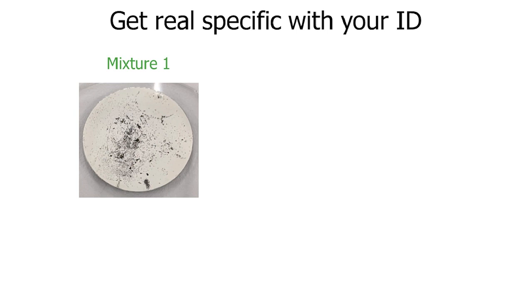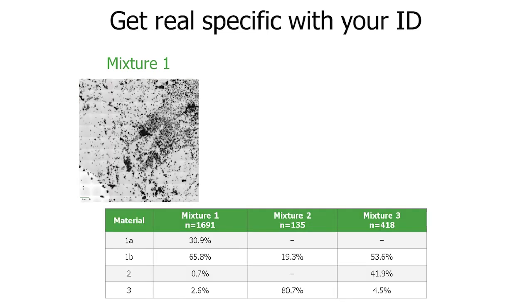The first mixed structural debris sample had many particles that varied in size. Hound identified just under 1,700 particles in about 90 minutes total. Of those, exactly 1,691 particles, a majority were material 1, with about a third being material 1A and about 2/3 being material 1B. A small fraction of the particles, under 1%, were material 2, while not many more were material 3.